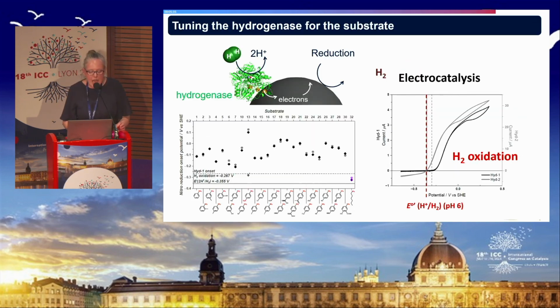Now, just very finally, going back to the electrochemical way of thinking about this, the hydrogenase that we used for this initial work was hydrogenase 1 from E. coli, one of the enzymes we've done lots of structural work on, but it has a small overpotential for hydrogen oxidation, meaning that it's losing a bit of that driving force from hydrogen. And we plotted the onset potentials for reduction of a wide range of nitro compounds, and all of these aromatic nitro compounds fall above the onset potential for HYD1, showing that HYD1 should be compatible with being able to reduce those, and indeed we see hydrogenation of the nitro groups for all these compounds.